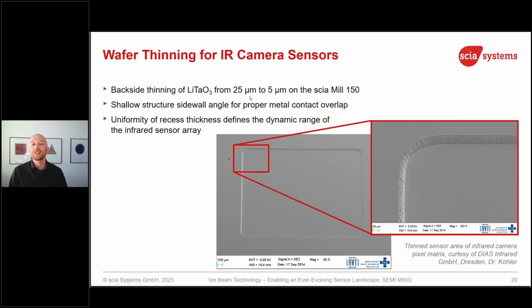And if we would continue, then those wafers or membranes could break easily. So the remaining 20 micrometers down to 5 micrometers are removed by ion beam etching, which is shown here also on those SEM pictures. And why do we need a certain sidewall angle, not 90 degrees? Because there needs to be also a metal electrode afterwards, where you can finally measure the voltage.